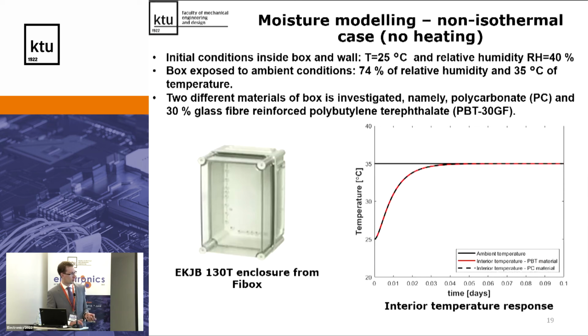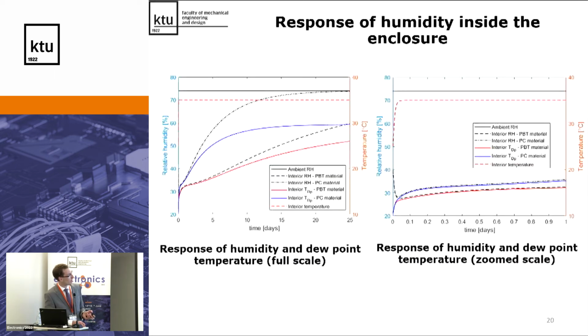And here I would like to show the interior temperature response. Of course, it's pretty quick, and there is no big difference. That's why I show them close to each other, because the thermal conductivity of these materials is very close, so we don't see a big difference, and it goes quickly. Here we can see the response of humidity inside. So we have ambient 74%, and here is the full scale and here is the zoom scale, because up to this point we have non-isothermal conditions. When the temperature stabilizes, then we have isothermal conditions.